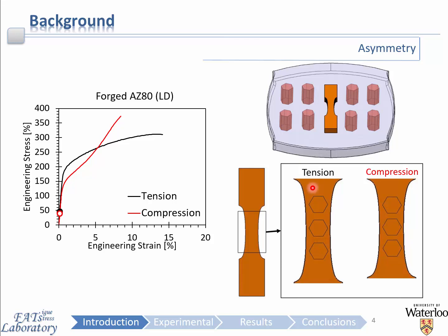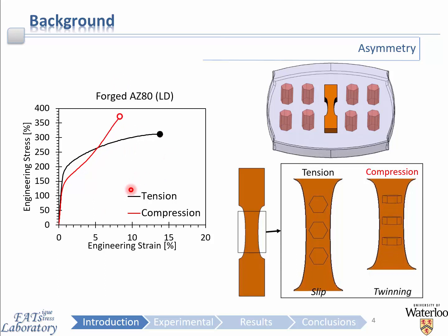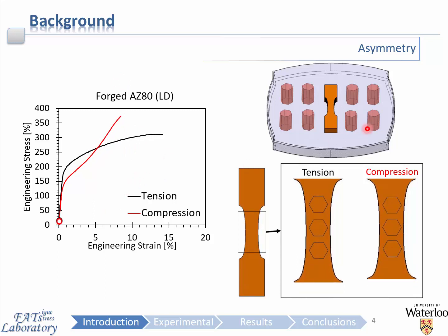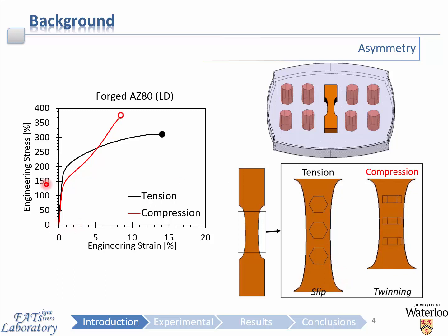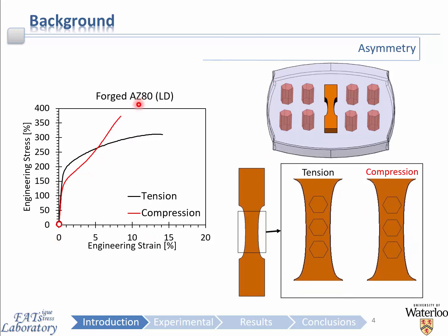One of the other unique features of wrought forms of magnesium is its unusual behavior at room temperature, almost always displaying a monotonic and cyclic response, which is both asymmetric and anisotropic. Yield asymmetry shown here is a phenomenon which is very common in most wrought forms of magnesium alloy, and the cause is linked to the hexagonal close-packed structure, as you can see here. In tension, basal slip is active, indicated by this monotonic curve, a hardening behavior here. In compression, twinning is active, which is manifesting itself as the sigmoidal hardening behavior here.